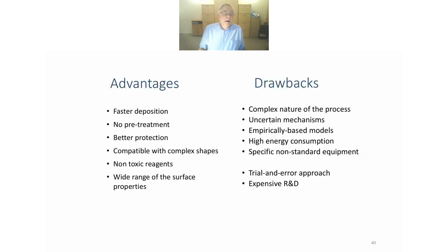Quite a powerful technique. It's fast, there are no pre-treatments, better protection, compatible with complex shapes. It's very safe, there are no toxic elements involved in it, and you can produce a wide range of surface properties. The drawbacks of it, and this is what lends itself to digitalization, it's a complex process. The mechanisms are somewhat uncertain. It's very empirically based. It has a high energy consumption. You spend a lot of power heating the water-based electrolyte. It uses rather specific non-standard equipment and has adopted in the past a rather trial and error approach with rather expensive R&D practices.